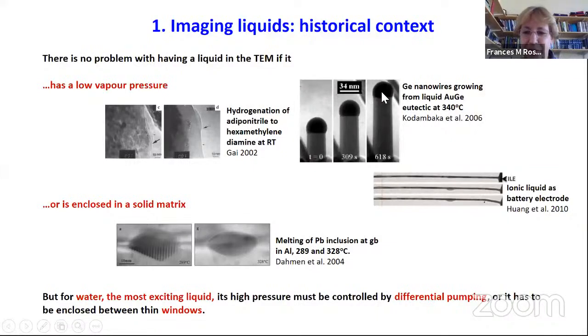This is gold germanium eutectic droplets that catalyze a semiconductor growth process. They're completely liquid. They just look amorphous in the microscope, but they're fine. They have a really low vapor pressure. You can also, of course, look at liquids enclosed in a solid matrix. So here's liquid lead, solid lead. You can look at these phase transformations. The lead is hidden away, trapped within a solid, no problem at all.